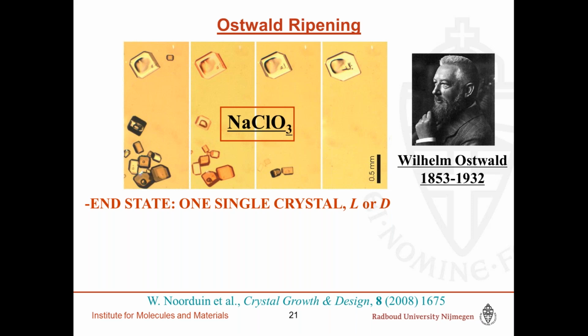So I would not know of any tricks unless you would have found in another way the enantiomer pure material, and then of course you can grow crystals from the enantiomer pure material, but perhaps you meant that this gives this amorphous compound already. That is not clear from the question. And what I wanted to say, once you would have gotten these enantiomer pure crystals from an enantiomer pure solution, then of course you could use them as seeds in a racemic solution and hopefully grow them further.